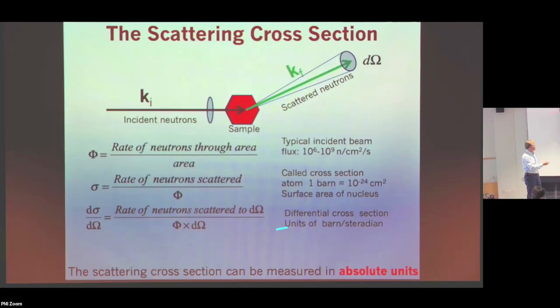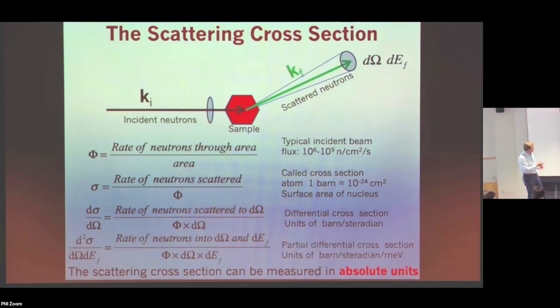So we are interested in the distribution of scattering into different solid angles. I'd like to see the angular distribution of scattering, and so I define this differential cross-section. The rate of scattering into a certain solid angle, d sigma, takes this form. And I can also resolve the energy of the final state, and that becomes this partial differential cross-section, which has units of barn per steradian per millielectron volt. That's essentially the thing we're measuring in the end, and we can do it in absolute units.